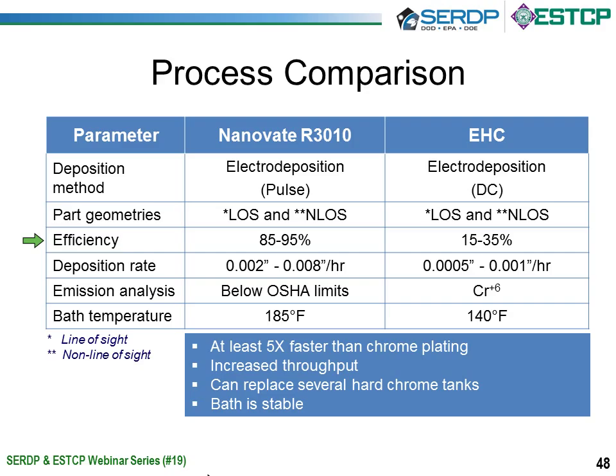But more importantly, the plating rates are extremely rapid. And that was some of the first feedback that we got from our production electroplaters, that they were able to produce coatings in times that would typically take 20 to 30 hours, and we could do that in a single 8-hour shift. Conservatively, we publicly state that it's 5 times faster or 5x faster, but I would say from a rule of thumb, we were seeing efficiencies upwards to 10 times when it came to plating rates.